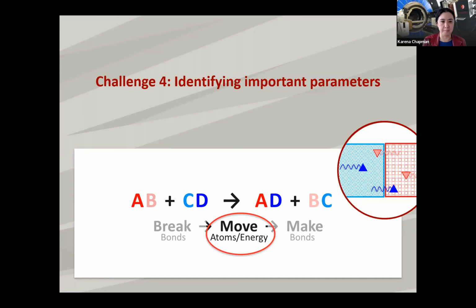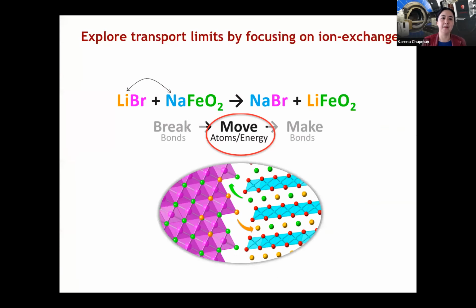Obviously, that's just a first approximation. The example we looked at here was a rock salt lithium salt, exchanging with a layered transition metal oxide phase, so exchanging the lithium for the sodium in this phase. For the first approximation, those matrices are staying the same, so we're just looking at the role of the movement of lithium and sodium with respect to each other in governing this reaction.